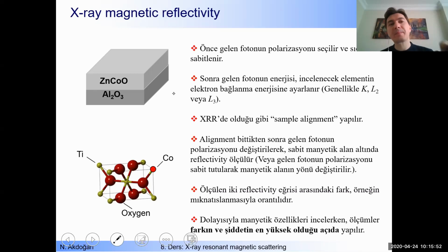So now let's start with X-ray magnetic reflectivity. During the last lecture, we saw X-ray reflectivity. So what is X-ray magnetic reflectivity? Everything is the same except the energy and the magnetic field. We have soft X-rays here compared to the normal X-ray reflectivity. In addition to that, we will apply a magnetic field to the sample plane.